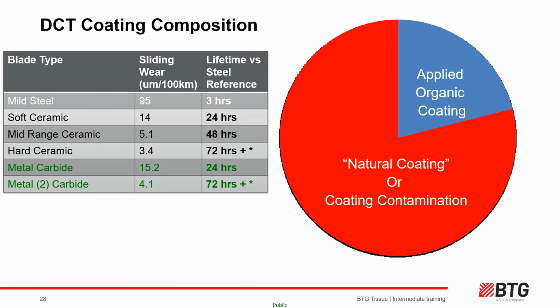So, a reminder, blue segment. Coating from the spray bar, which is hopefully applied in a controlled and CD even manner with a stable operation. It controls the sheet onto and off the Yankee, protects the Yankee and helps to achieve product specification and blade lifetimes for as long as safely possible. It needs to dominate and augment any natural coating coming from the tissue making raw materials.